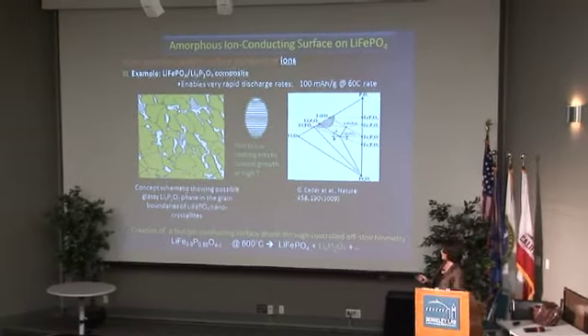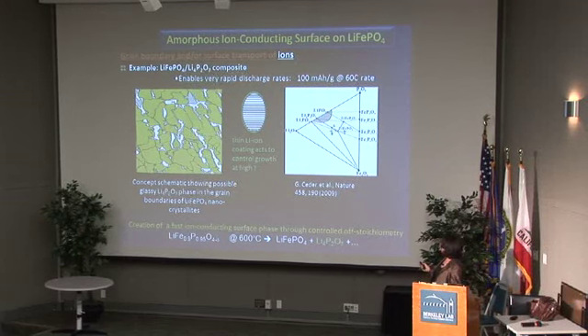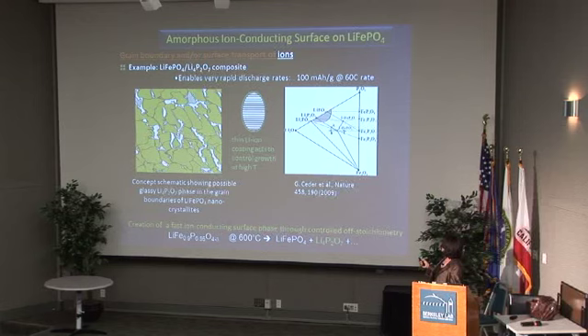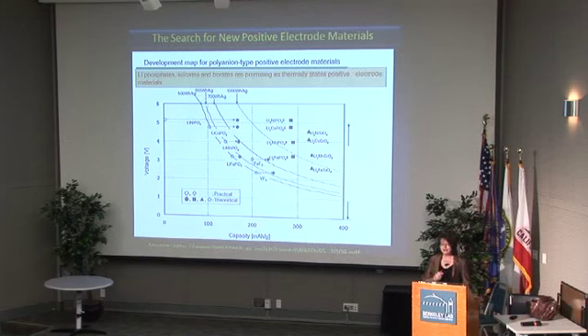So this is just the same schematic. I just used the same cartoon showing now the growth of Li4P2O7 on the surface of these particles. And this is reputed to be a fast ion, or at least a fairly good ion conductive material. So instead of forcing out the formation of the FeP2O7, he forced out the formation of the lithium iron pyrophosphate by simply going substoichiometric in iron. So the same sort of idea. And the other concept here is that this glassy coating of this iron pyrophosphate, rather, seems to control growth. So they were able to produce defect-free materials with this ion conductive coating. This material has enabled very rapid discharge rates with good capacity, and is sort of a bit controversial, so I won't get into it. So where do we go from there?